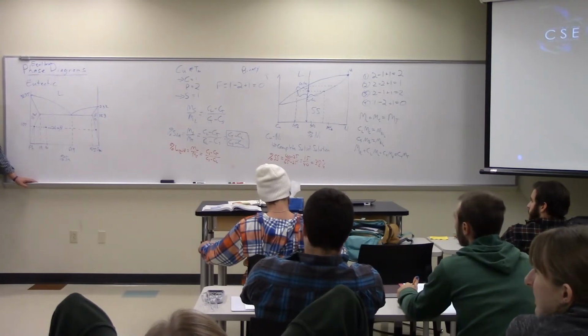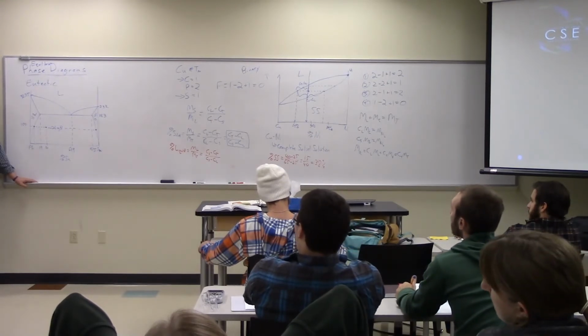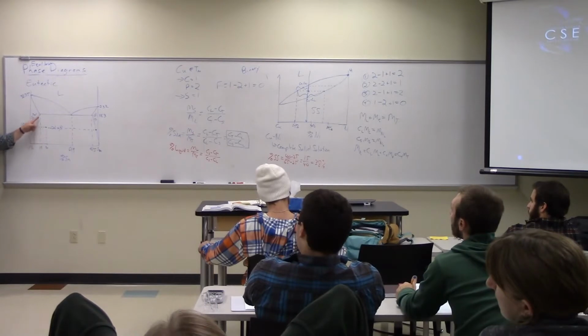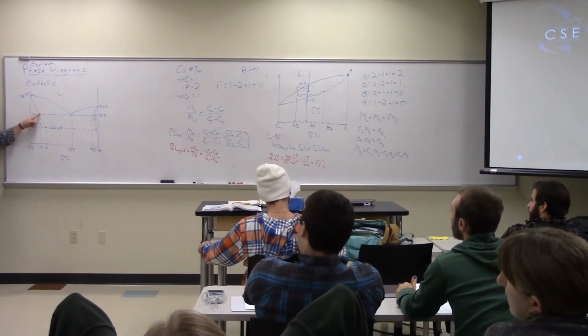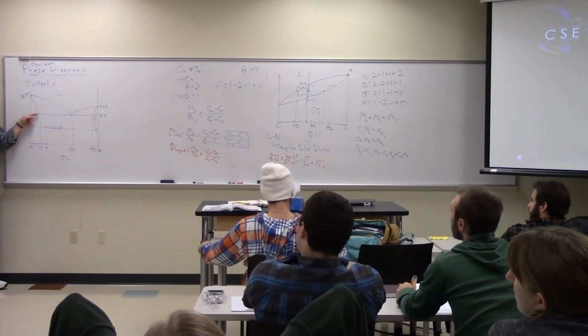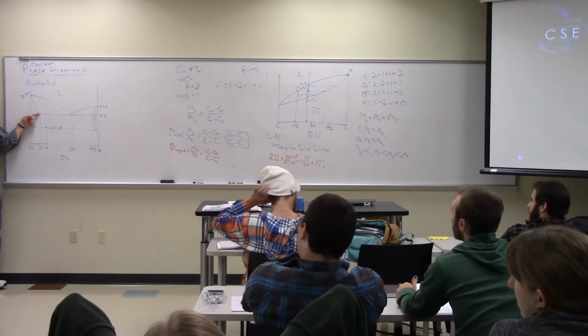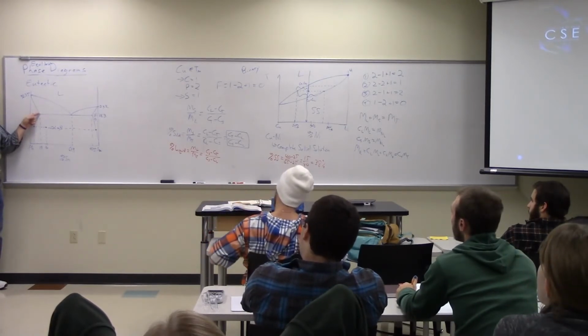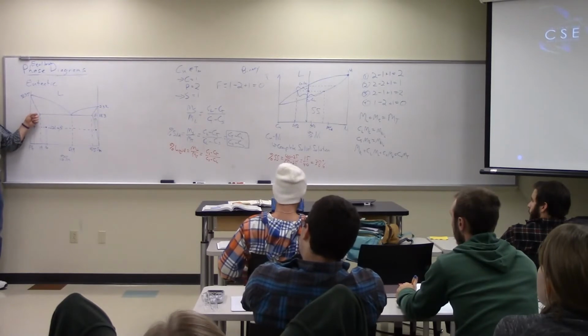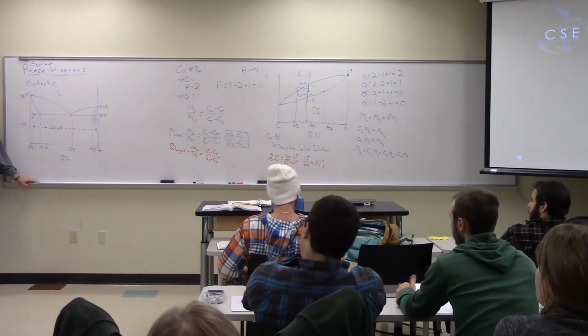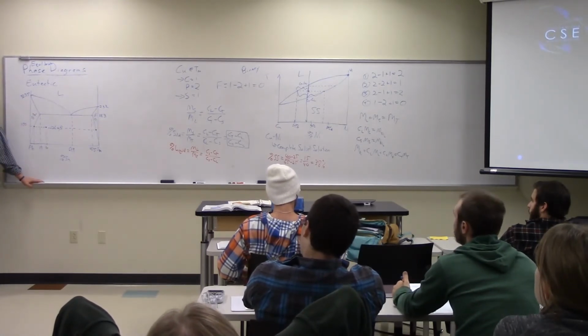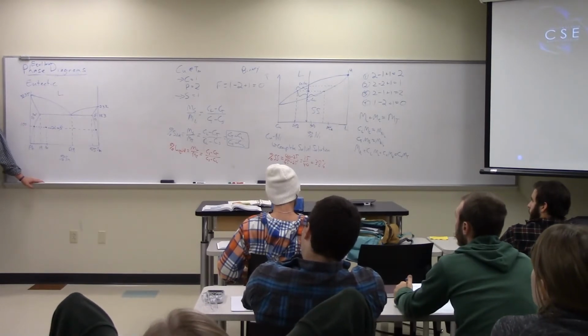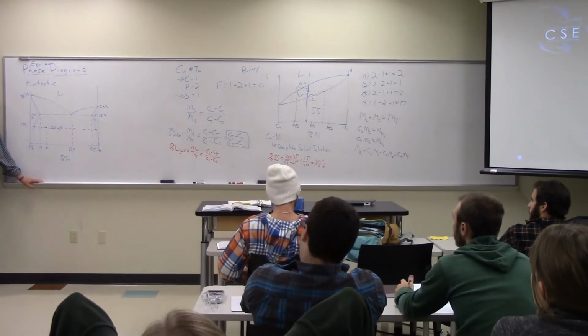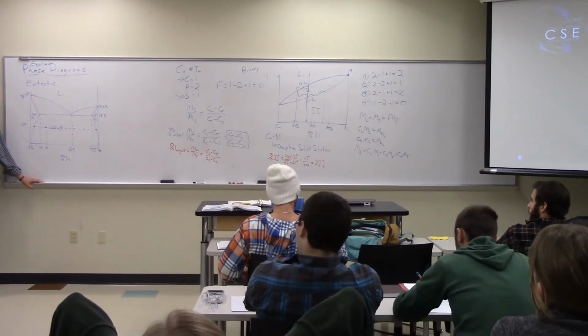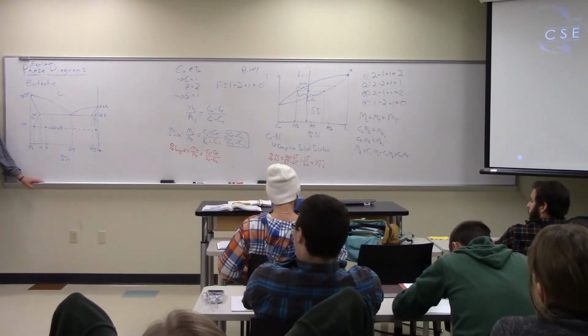What is the 19, the line of the 19? That 19 is the horizontal coordinate at that point. It is the most tin that I can dissolve in lead at any temperature and still have it be a single phase of lead, alpha. So in other words, there's 19% by weight tin atoms distributed uniformly throughout a lead matrix. But they're isolated atoms, they're not a separate phase, they don't agglomerate together.